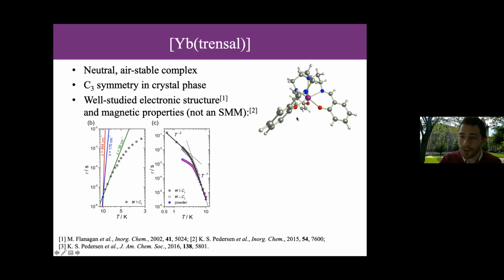It is most certainly not a single molecule magnet. This is the really nice image from, I can't remember if it's the Inorg Chem or the JACS. No, it must be this Inorg Chem from Casper's work, where you have luminescence that tells you that the first excited state is at 470-odd wave numbers, but yet if you assume you have this Orbach thing where you draw a linear slope on an Arrhenius curve, like everyone was doing for a decade for lanthanide single molecule magnets, you get a barrier that's just absolutely ridiculous and makes no sense, because it's nothing to do with Orbach relaxation. So you plot it on a different scale, this log-log plot, and you see it's linear, which means you have this power law regime. And so this is really just all Raman two-photon dynamics at low temperatures. So there's no Orbach SMM behavior in this thing.